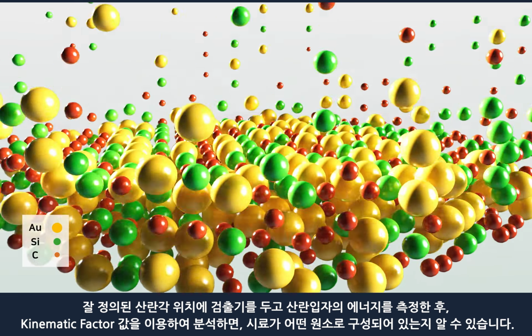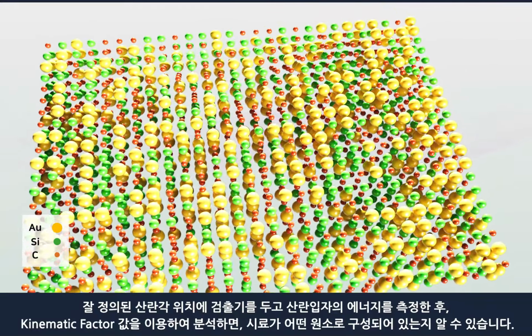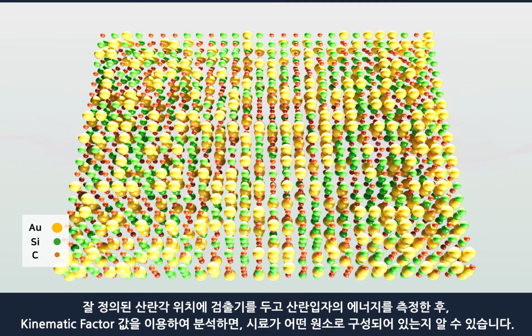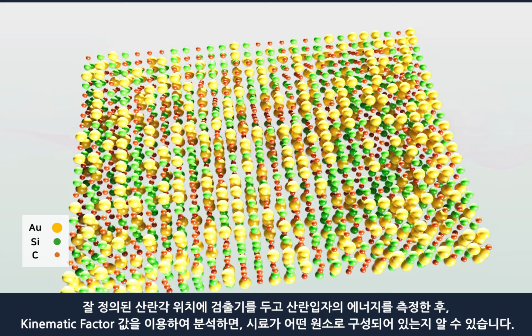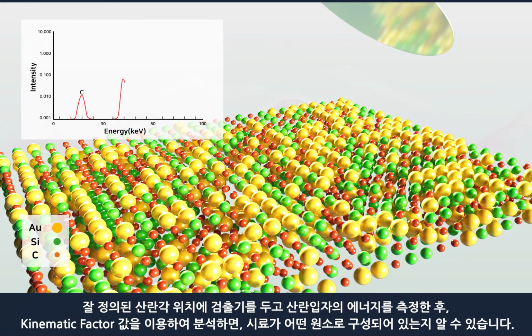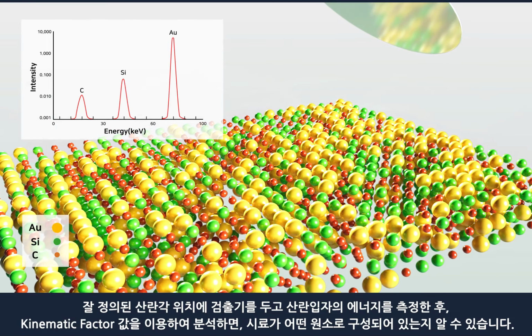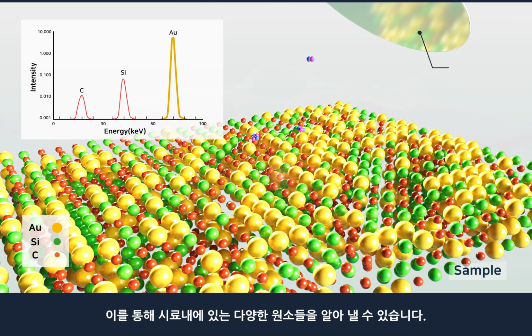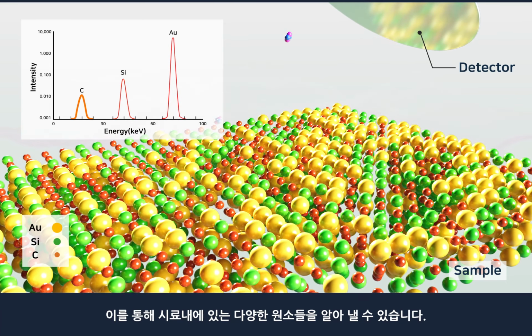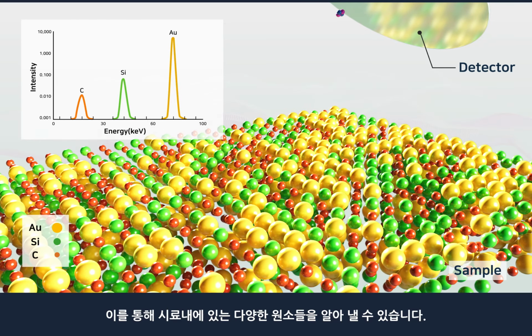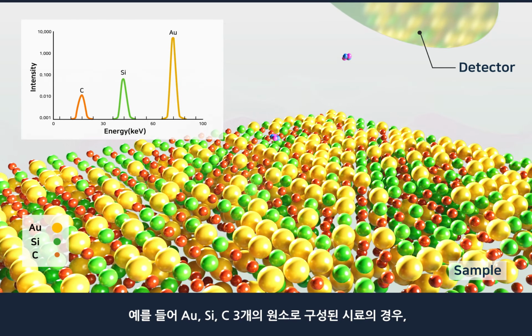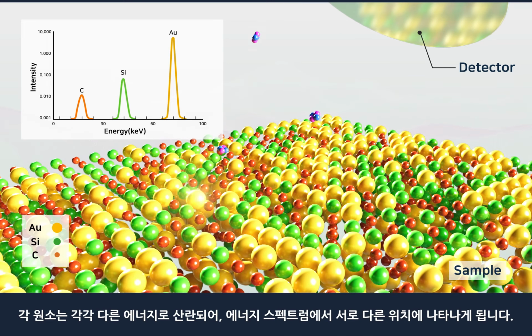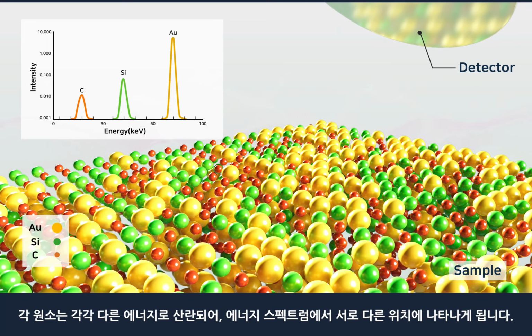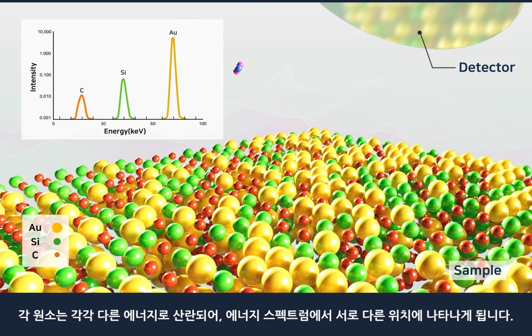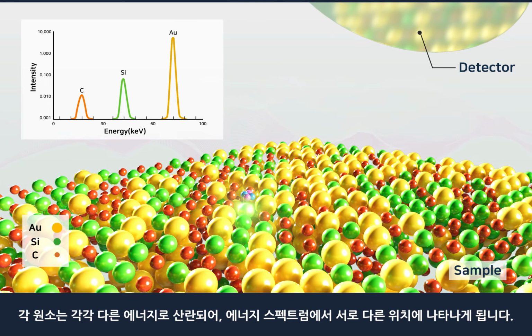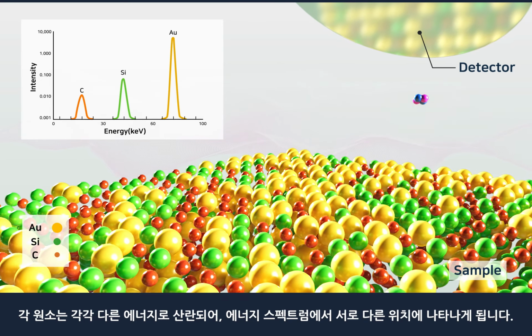After measuring the energy of the scattering particles by placing the detector at a well-defined scattering angle position and analyzing it using the kinematic factor value, the elements of the sample can be determined. This will enable us to determine various elements within the sample. For example, in a sample comprising 3 elements, ions are scattered by each element, resulting in different energies, and each spectrum appears at a different position in the energy spectrum.